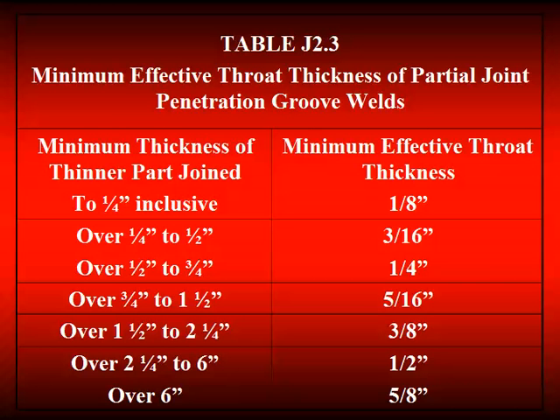You put in a weld that small, it's going to solidify and cool so fast that heat affected zone could be a problem. So to make everything work together, the code says, okay, do your design calculations, specify the throat dimension, come back and double check against table J2.3, make sure you've made it at least that minimum size. The reason it's there is oftentimes what you calculate is actually smaller than this. So you go back and you may have to increase the weld size to meet this minimum requirement.